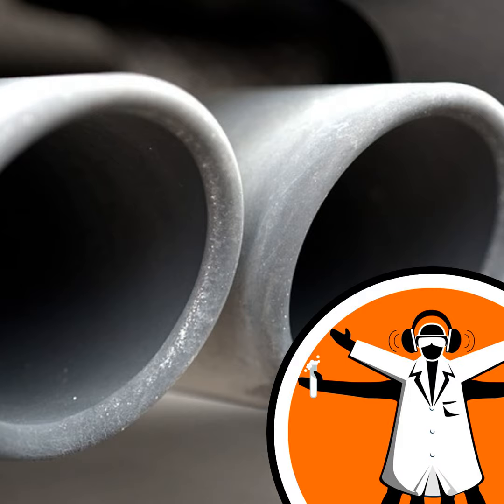That's a discovery, that's a potential use. Their analytical techniques showed that platinum atoms had actually become small platinum nanoparticles. And the same size platinum nanoparticles were giving different performance for the reaction, depending on the route. Now, they found a high temperature route, where they made it at 800 degrees Celsius, worked the best, because they found the cerium oxide was making a difference.